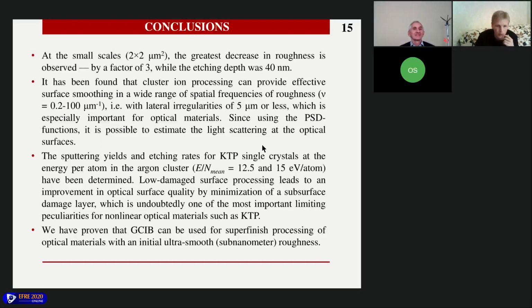Using the PSD functions, it is possible to estimate the light scattering at an optical surface. And we determined the sputtering yields and etching rates for KTP single crystals. We see that low damage surface processing leads to an improvement in optical surface quality by minimization of the subsurface damage layer, which is undoubtedly an important limiting factor for nonlinear optical materials such as potassium titanyl phosphate. And we have proven that gas cluster ion beams can be used for superfinish processing of optical materials with initial ultra-smooth roughness.